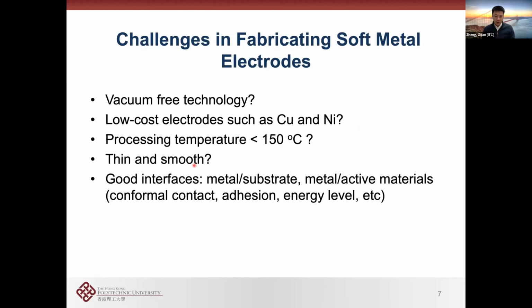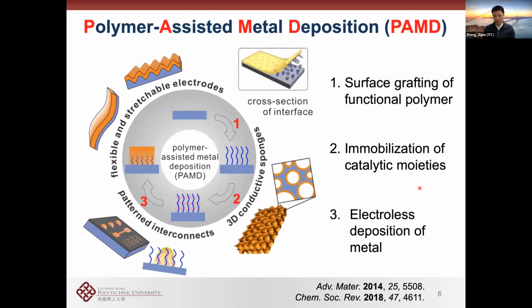Can we make it thin enough and smooth enough to yield very high performance devices, which is quite critical? Can we have good interfaces between all these materials, for example with the substrates, to have good adhesion? Can we have a good interface with the active material so that they can perform better? Right. With all these problems, having good, high-performing soft metal electrodes has been quite a challenge in the last 10 or 20 years. So this is what we've been really working on.